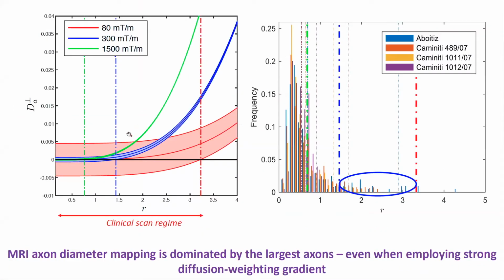And that's shown over here. I did some simulations on how sensitive we are to axon diameters by plotting the intraaxonal diffusivity versus the radius for different scanners. A clinical scanner, 80 millitesla per meter, the Human Connectome scanner, 300 millitesla per meter, and preclinical systems with gradient strengths of 1,500 millitesla per meter or even higher. In a clinical scan regime, where the gradient strengths are limited to about 80 millitesla per meter maximally, we can only measure axons that exceed 3 micrometers in radius.